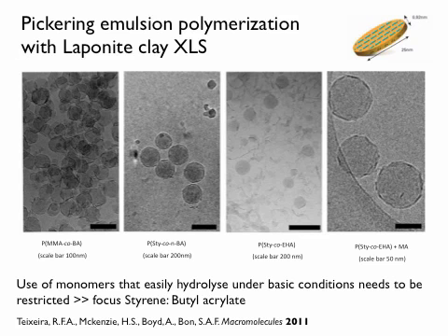What you see here on the left-hand side, PMMA with butyl acrylate, you can clearly see that the clay platelets are beautifully decorated around these soft particles. You can even see the particles are soft, because the platelet is hard and it distorts the particles from being spherical. It's quite nice. Styrene butyl acrylate also works quite nicely. You see the clay platelets beautifully around.